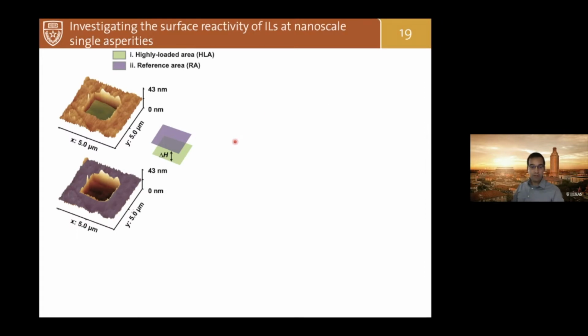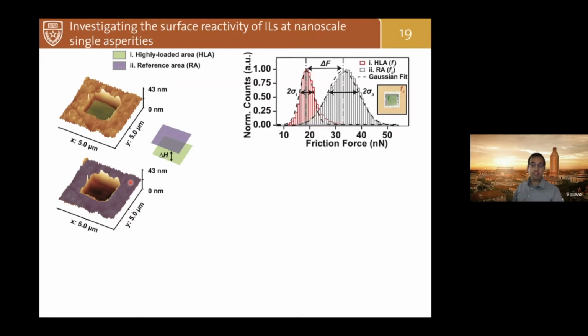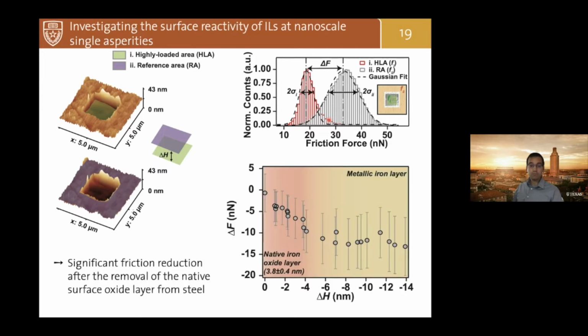So we tried to quantify this by computing the height difference between the area scanned at high loads and basically the reference area that was not scanned at high load. But we also computed the change in friction by looking at the friction force distribution and computing the difference between the distribution in the region that was loaded at the maximum load and the reference area. The key result is in this plot at the bottom right, where you see the change in friction as a change in height. And what you can see is a slight progressive decrease in friction until 4 nanometers, you remove the first 4 nanometers of the surface.